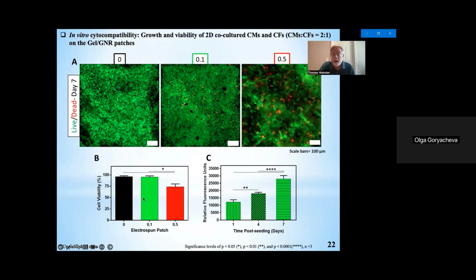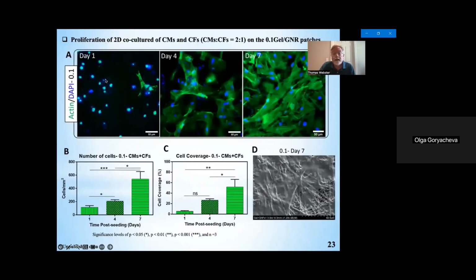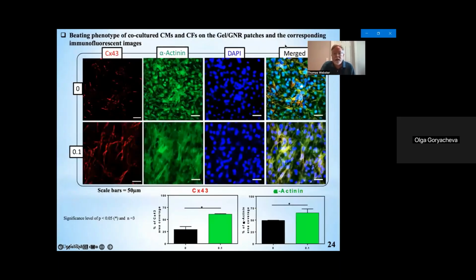So we've often stuck to our animal studies for this 0.1 weight percent graphene nanoribbon in gelatin patch, but you can see they do grow on those samples with time. In fact, day 1, day 4, day 7, the cells are continuing to grow on the surface, continuing to spread out and look very, very healthy. And again, this is on the 0.1, our optimal material formulation that we've made so far, gelatin graphene nanoribbon patch.